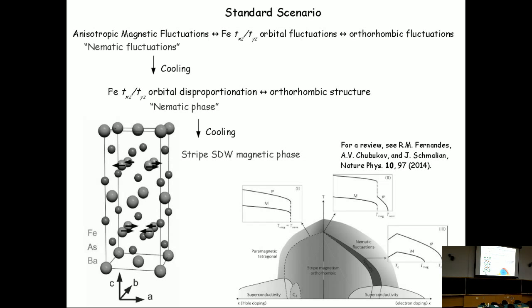Okay. Yeah, sorry, I have a question about a clarification of your result. I'm a theorist, I'm not an expert in the field. To me, the issue was whether the nematic transition was driven by charge or by magnetic order. Your results support magnetic order, differently from other results that were saying it was charge driven. Is this the final point of your talk? And if it is, may this depend on the material? I mean, in one material this transition might be more driven by charge and in the other by magnetic order, and that's the reason why you see the peak at different transition temperatures.